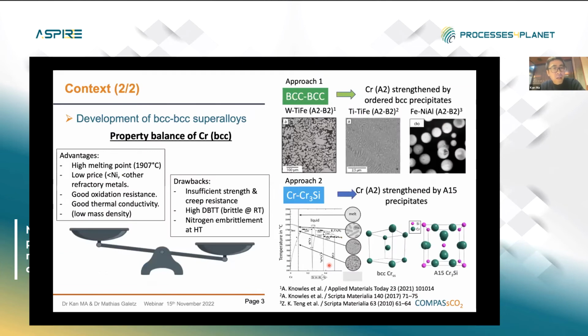And why chromium? If we look at its properties, its advantage is quite obvious. It has a high melting point, 400-500 degrees higher than nickel and iron. It has a low price, and it has good oxidation resistance and also good thermal conductivity, which is critical for heat exchangers. But its drawbacks are also quite obvious. Its lack of strength needs to be addressed. It is brittle at room temperature and has some nitrogen embrittlement at very high temperatures.